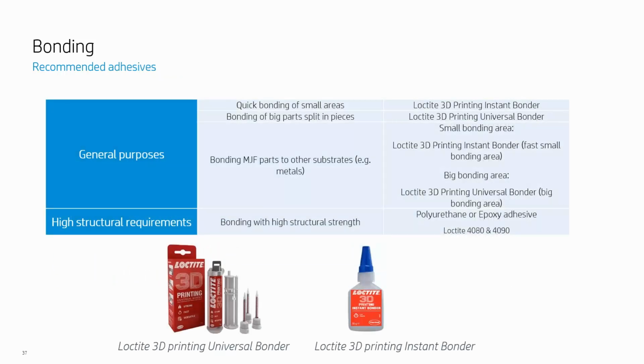And then some of the recommended types of glue. We've worked closely with Henkel or Loctite, and the two that we mainly prefer, if you don't need a really superior bond strength and you need to do it very quickly, you're going to use the Loctite instant bonder, which is essentially a CA glue formulated for 3D printed parts or additive manufacturing parts. And then if you need a stronger bond, you're going to look at a universal bonder, which is like a hybrid glue of CA and different types of epoxy. And if you need the highest structural strength, then you will go to a polyurethane or epoxy and use the Loctite 4080 or 4090 or a similar product. It doesn't necessarily need to be Loctite, but these are the ones that we've found work really well.